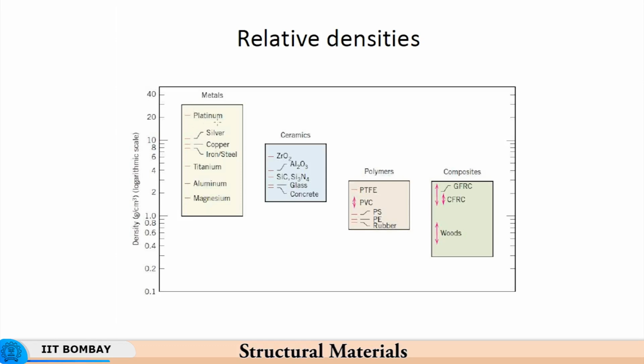Here tungsten is not mentioned, but then there are tungsten, rhenium, vanadium. So, many of these materials which are refractory alloys, molybdenum and similar materials, these high temperature materials have high density, and they are therefore able to withstand stress at high temperature. So, high temperature creep is withstood by these. Ceramics are oxides and oxide nitrides of different metals, or they are glass, concrete.